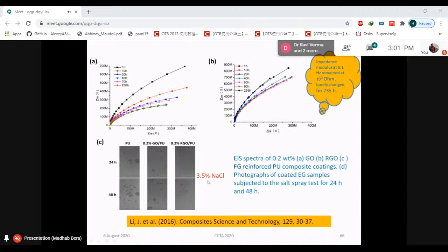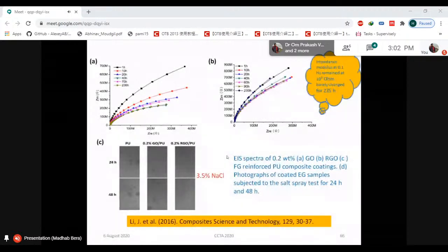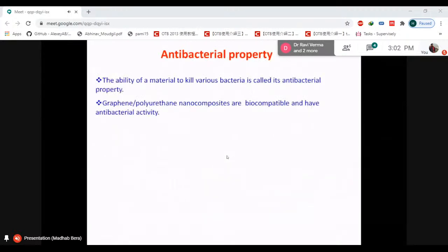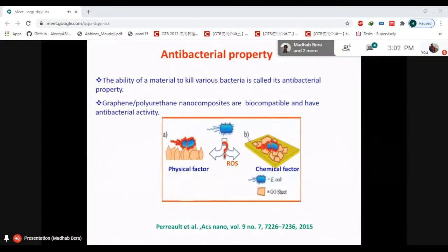In the salt spray chamber, they found visually that the corrosion is decreased in the case of both GO and RGO, but the reduction is much more prominent in the case of 0.2% RGO filled polyurethane nanocomposite. This corrosion resistance property is also very important for coating applications. Now the antibacterial property. Antibacterial property is the ability of a material to kill bacteria. In the case of graphene based materials, the most widely used mechanism is the rupture of the bacterial cell wall, as you can see from this figure.